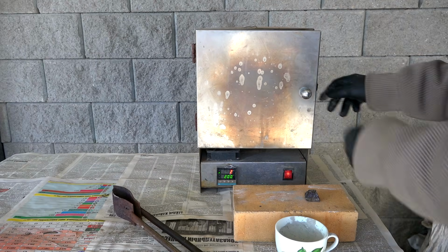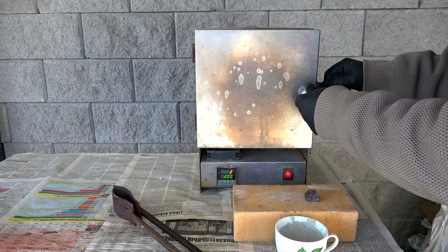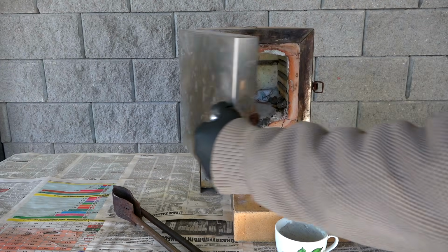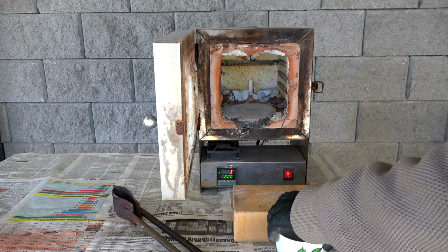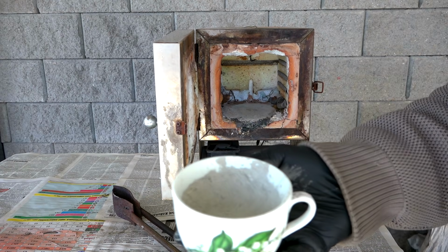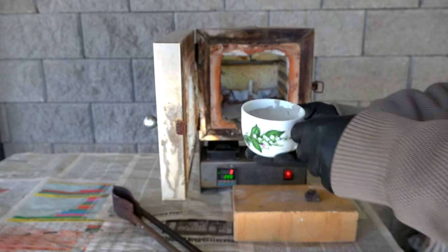To begin with, I warm up the cupel to 800 degrees and check whether cracks have formed or not. If cracks appear, they can be fixed with a simple mortar while the cupel is heated, and only after that can you put the lead alloy in it.